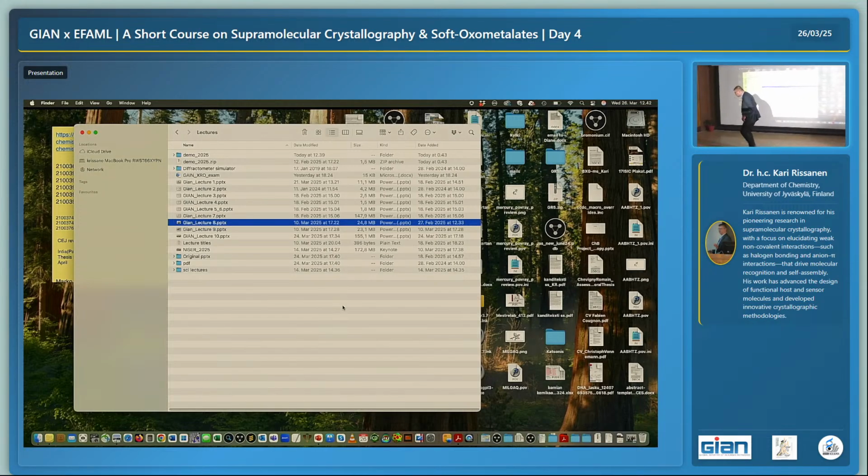One method for crystallization is the vapor diffusion method. In this method, we select a small chamber inside a big chamber. In the small chamber, we select a solvent where the molecule is totally soluble. And in the bigger chamber, a solvent where it is less soluble, because it will create vapor pressure but not interact, or interact less, with the molecule. That's the idea.